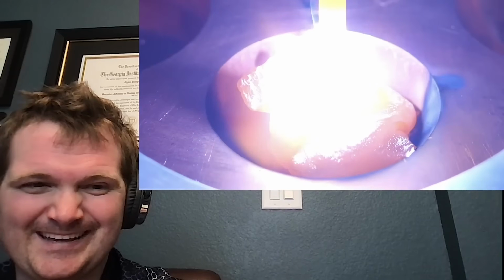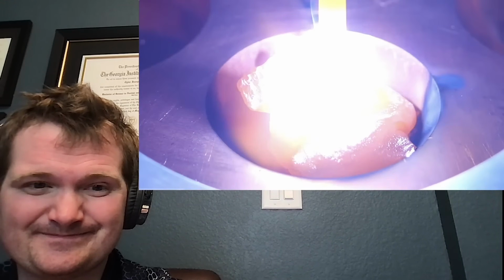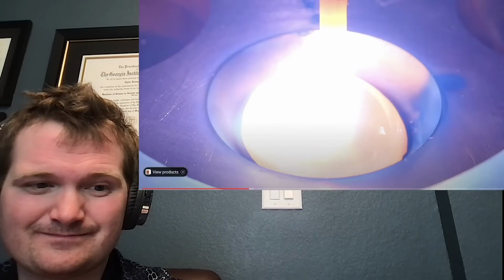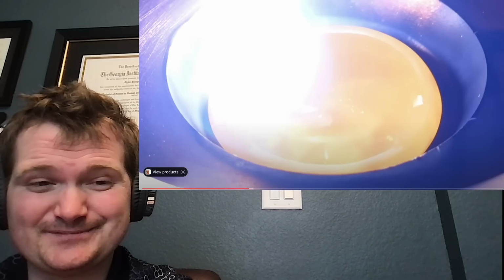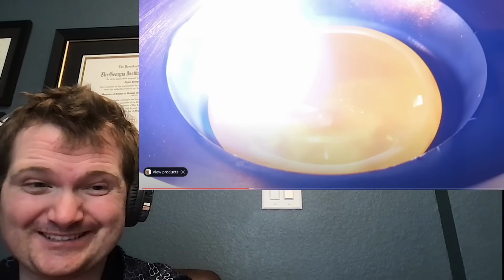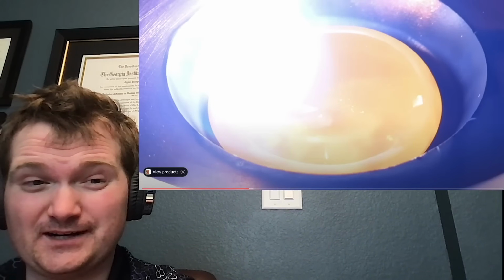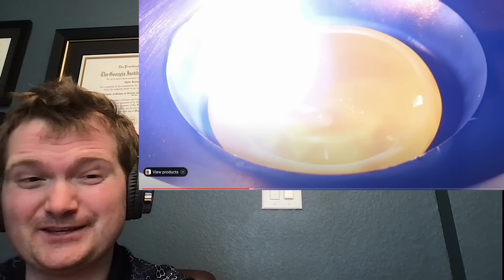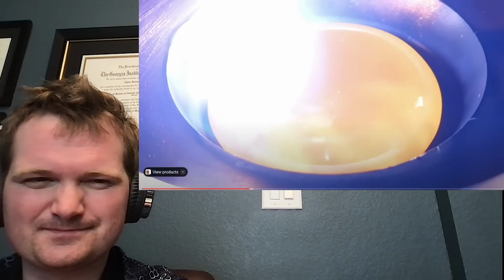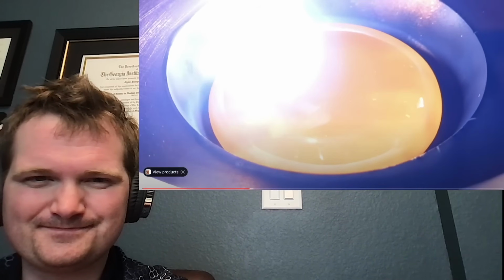What I thought was even more impressive, though, was that in less than a minute later, it had completely liquefied, and I had an absolutely ripping hot blob of iron. Well, arc welding can get over 5,000 degrees Celsius, and then you have plasma torches, which are upwards of 25,000 Celsius, so we're talking far hotter than the surface of the sun. But nothing close to the core or the corona for that matter, which is interesting. A lot of people make comparisons to the surface of the sun. It also didn't seem to have any oxides forming, which told me that the inert atmosphere was working, and overall, I was very happy with my purchase.